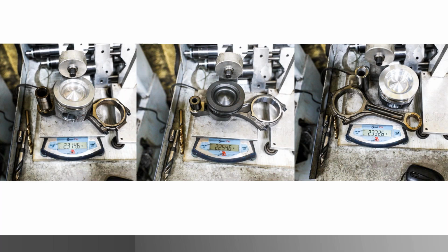That means you are now running about 1 thou to 1.5 thou piston to wall clearance on an aluminum piston. There's a problem with that. It doesn't work very well, and it certainly doesn't work if the guy winds up putting a tuner on it or anything else. For boosted applications with a cast aluminum piston, I would want to see 3 thou piston to wall clearance, given that bore size and everything. It's typically what I'm going to run. So that's something to keep an eye out for. And you're starting to see the theme: Ford is making all the new stuff, but they're not supporting the old stuff. There has been such a huge difference in the design changes of this engine that it doesn't cross over. It'll bolt on, no problem, but that's where it begins and that's where it ends.